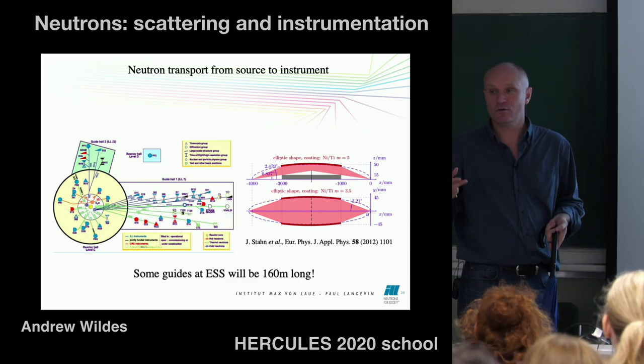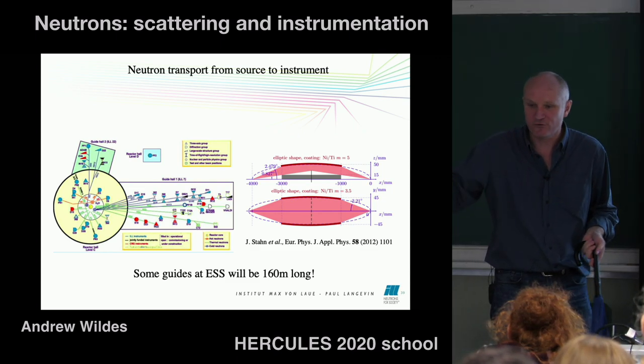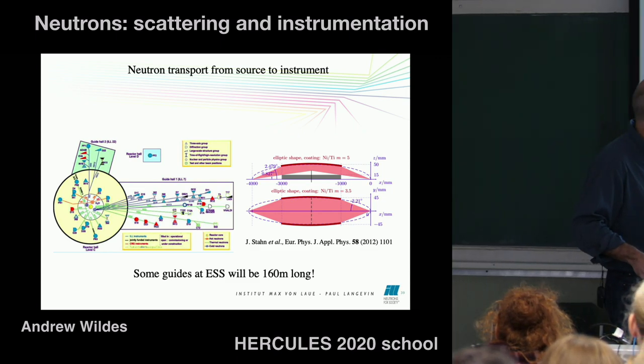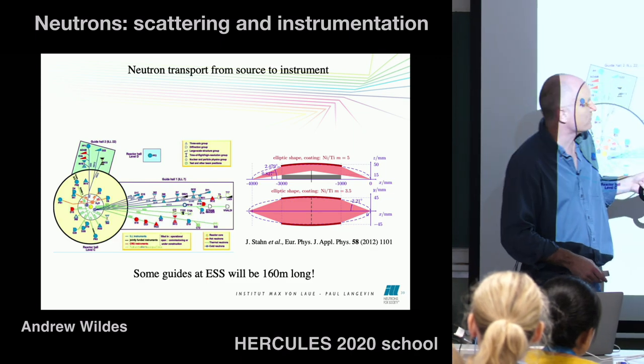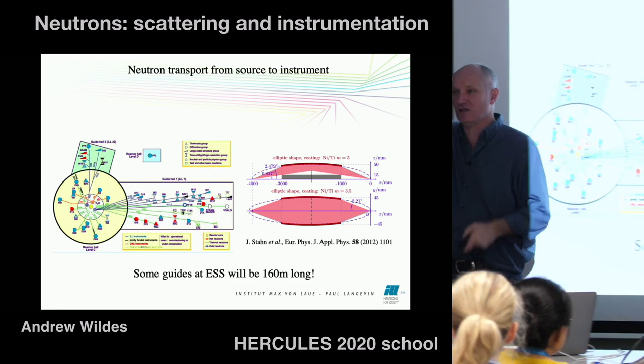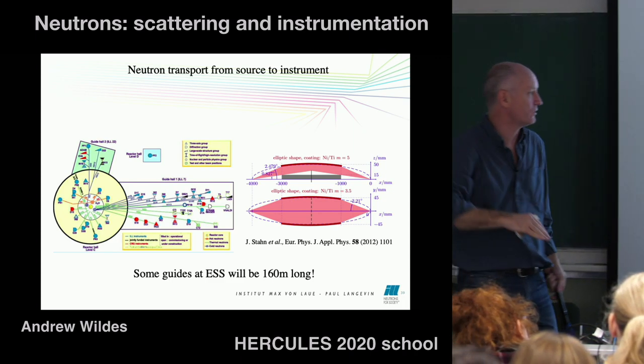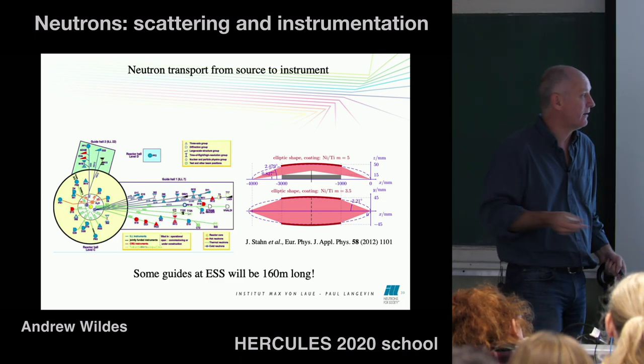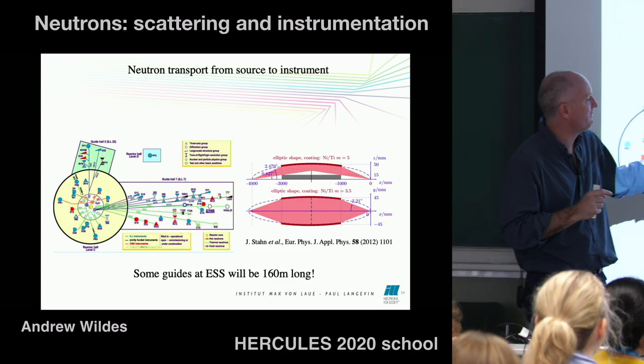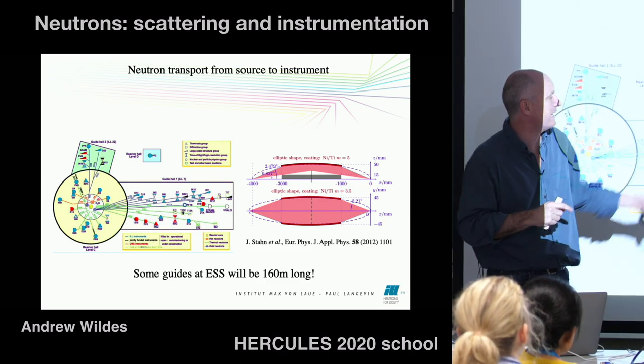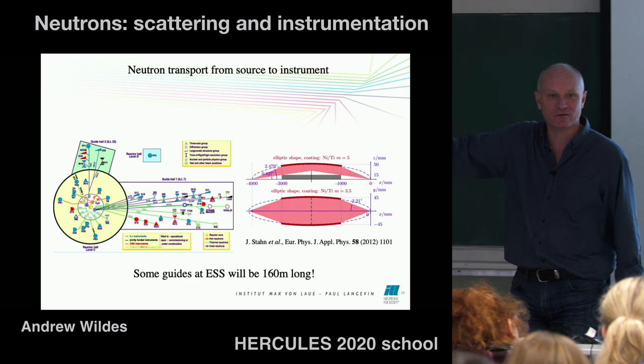And people are able to do optics with this as well to try and boost the performance of the instrument. So this is a relatively new proposition here by Jochen Stahn called the Selene concept. He's doing point-to-point focusing using a parabolic mirror, in this case for neutrons. And it works. It works quite nicely under certain conditions. You have to be very careful here. You've got very small angles, if you look at them. They're really glancing angles, less than a degree.